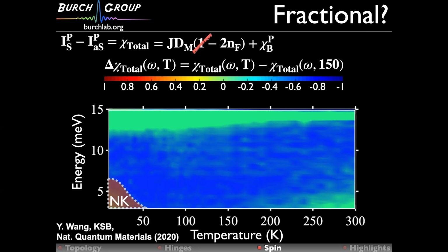Right. But most of your measurement is above the Néel temperature anyhow, right? Which is like 6-7 Kelvin. Yes, I'm completely above the Néel temperature. That's right. So there's no inconsistency, is what I'm getting at. The difference is that I have the energy and temperature resolution to tell the statistics. I see.